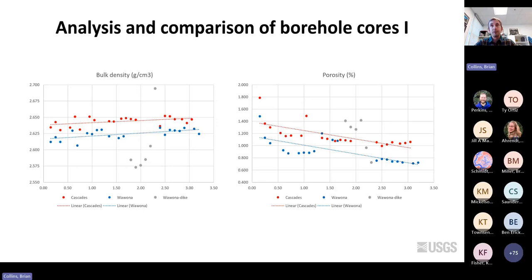In red, you can see the results from the Cascades, the south-facing side, and in blue you can see the results of the analysis of the cores from the north-facing Wawona side. On the horizontal axis, you have the depth of the sample that has been analyzed, and on the vertical axis, you have the corresponding properties. So the bulk density doesn't differ a lot, but the samples from the south-facing slope from Cascades have a little bit higher density than the north-facing slope. Also, I forgot to mention that in gray, we have the results from the part of the dike and the diorite that we didn't use in the analysis because this is a different material.